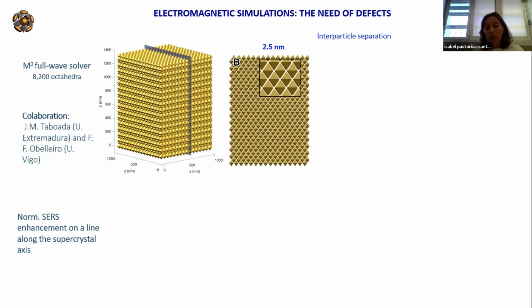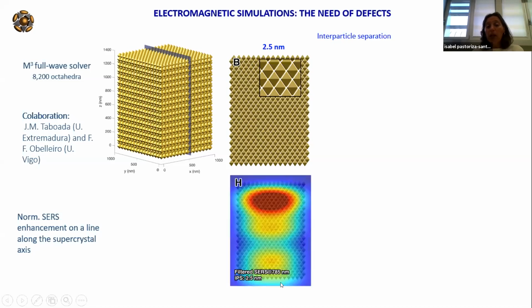So this image here corresponds with this plane drawn in this scheme. And now, if we check the SERS enhancement, these calculations were performed considering the experimental illumination conditions. We observe that the most intense signals are concentrated at the surface of the supercrystal, and this is probably due to the penetration of the light. The light cannot really penetrate inside of the